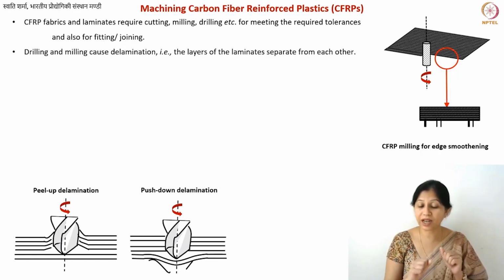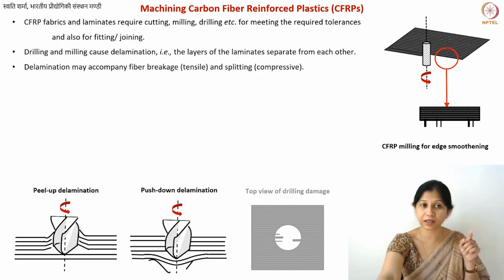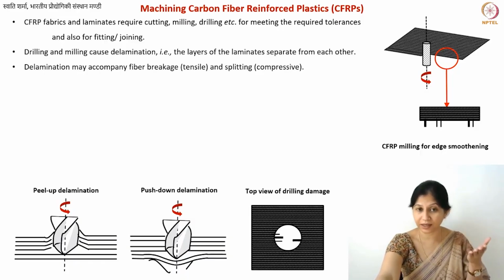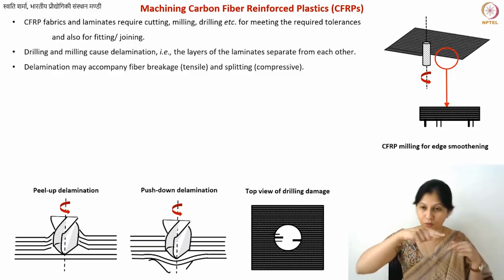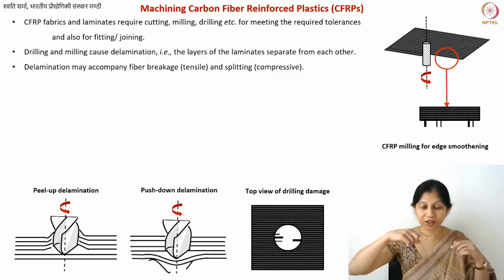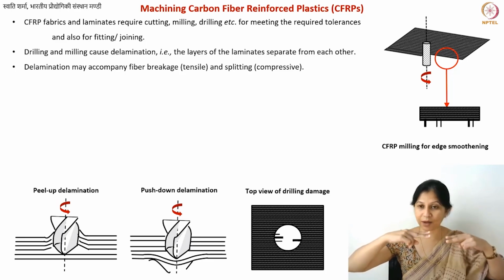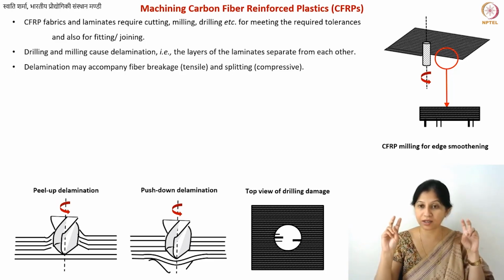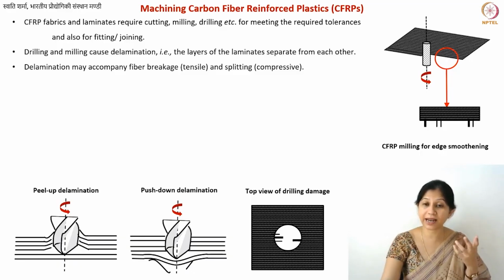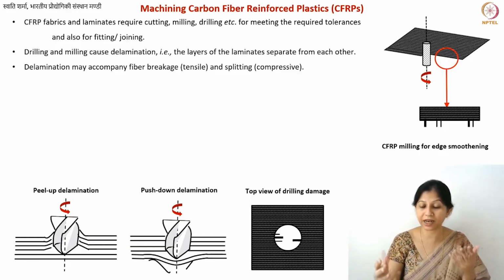So these are the two types of delamination. If I take the top view of this second one, push down, then you will see that you were able to drill the hole, but you did have some fibers that are not removed. So some residual fibers you will always see. Why did that happen? Because these fibers were delaminated at some point.